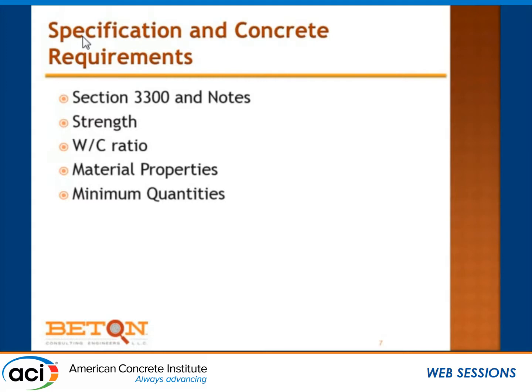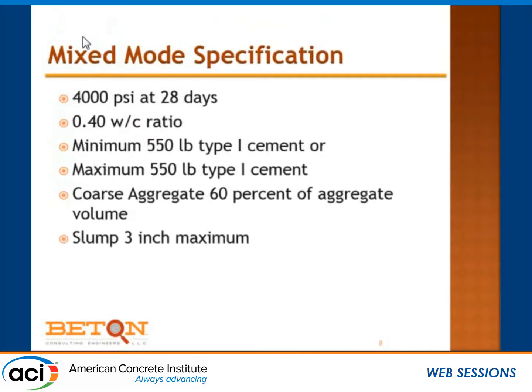And on occasion, or most of the time, we'll see a specification for strength, because the code says you need it, and a specification for water-to-cement ratio, because in many cases the code says that you need it, but not in all cases, and some material properties. We want Portland cement to conform to some obscure and out-of-date specification, C150-95. But we also may have other codes or requirements, and one of the requirements is that we put in minimum quantities.